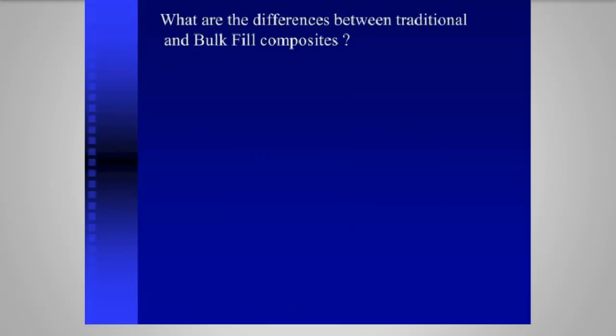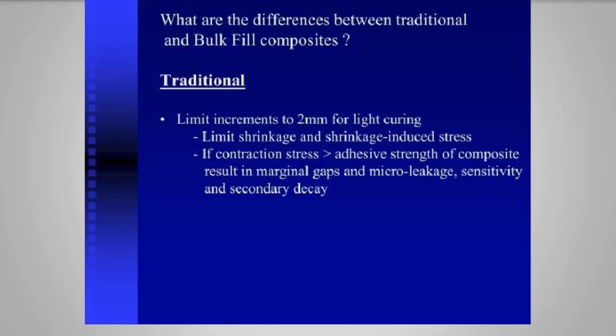What is the difference between traditional and bulk fill composites? Everybody does direct dentistry, so we understand what we're doing. Traditional composite relies on increments of 2 millimeters for light curing. And we limit the volume of the materials to limit the shrinkage and the shrinkage-induced stress that goes to our adhesive level. And if the contraction stresses are larger than the adhesive strength of the composite, then you